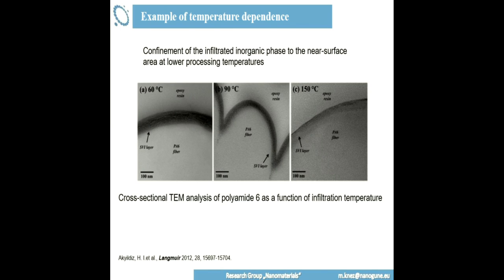polymer. I did not say at the beginning of this part that this is something which happens really very, very often in polymers, and you may or may not want to have this. Basically, the whole infiltration story started with an undesired observation from Steven George's group that if you want to coat polymers by ALD, you have something diffusing in. So we picked up on that and looked a little bit further into that because we wanted to have it then afterwards. We wanted to have the infiltration, so we modified our processes in order to get the infiltration. But you may, in your work, want to have it or not if you do treatment of polymers by ALD.